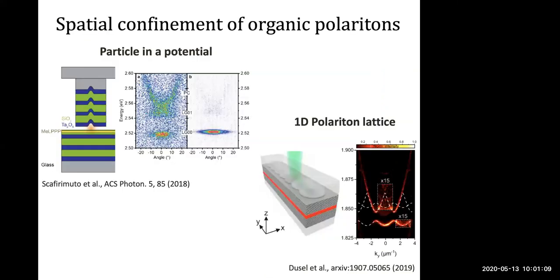And then very recent work has studied the formation of organic polariton condensates in confined geometry. These are normally fabricated by etching a little dimple in one of the back mirrors before the fabrication of the actual dielectric mirror. So here you can see the confined modes due